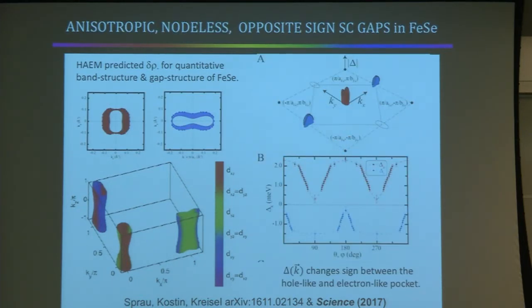So now this is what we see. Here, there's a gap which is highly anisotropic. It's 15 times bigger here than there. And here, we see another gap which is highly anisotropic, but it's normal in orientation to the first one. So if I plot delta as a function of k, the overall gap structure looks like this. Or if you don't like this bishop's hat picture, the gap on this band as a function of angle looks like this. The gap on this band as a function of angle looks like this. And they're of opposite signs.